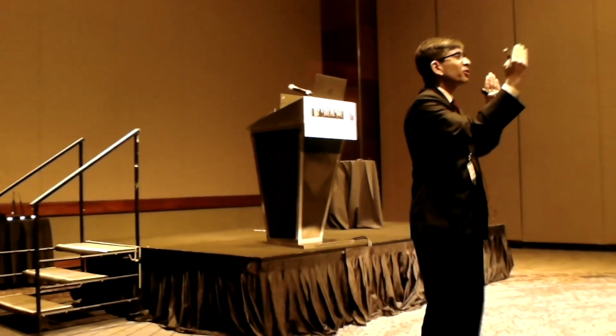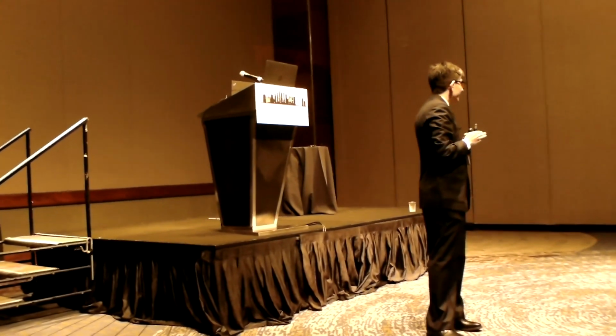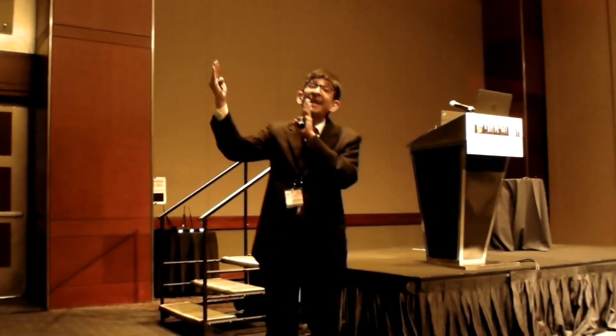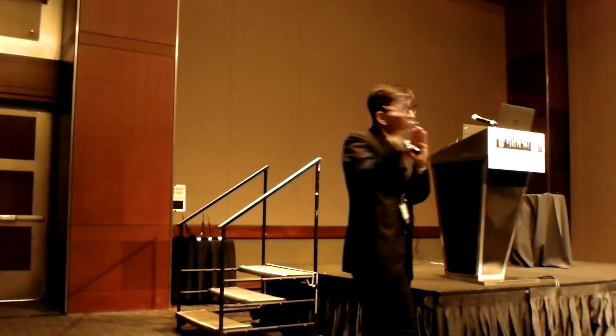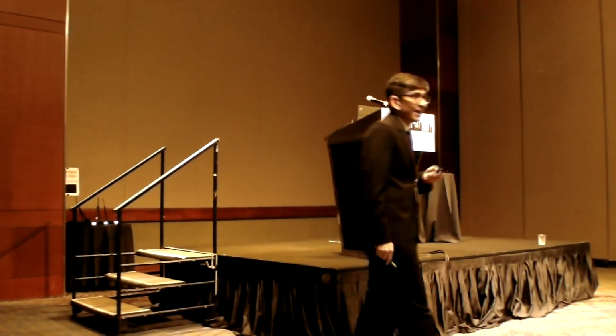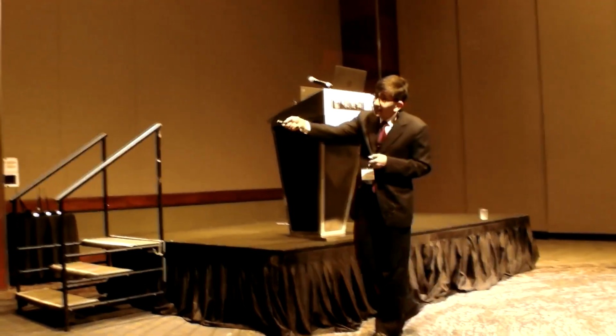It means that the catalyst deactivates non-selectively. And what I mean by non-selective deactivation is the number of sites changes, but the characteristics of the sites don't change. It's the same catalytic site, it's just I keep reducing the number. So my bed effectively keeps becoming shorter and shorter as my catalyst deactivates. And this non-selective deactivation allows me to essentially get a profile in time, which gives me an axial profile in the reactor. So the temporal evolution of the products is actually giving me what's happening in a sequential reactor as I go along the length of the bed. And this is the virtue of understanding what the deactivation characteristics of this material are. I see data that look like these.